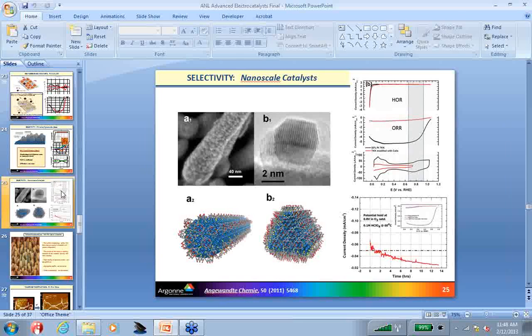Regarding the potential window of stability, in the case of platinum bimetallics, what we know is that there is what we call a gray zone, and these catalysts are stable up to, I would say, 1.1 volts. If one goes above 1.1 volts, then corrosion of both platinum and especially the non-noble 3D elements would happen. Now, everything we have right now is on very well-defined systems.